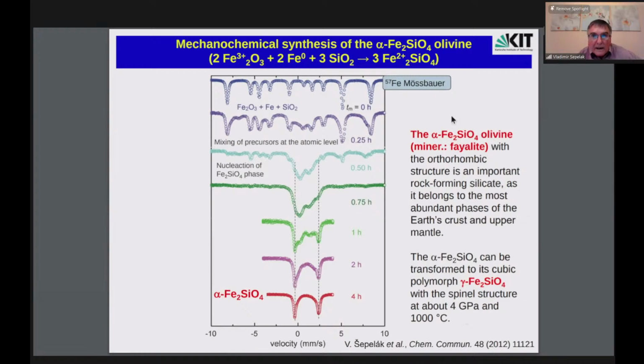But I only mention here its mechanosynthesis followed by Mössbauer spectroscopy. Again, we started with 3 precursors, and an internal redox reaction took place between iron 3+ in hematite and metallic iron with 0 valency. That means in the end we have iron in the divalent state, ferrous ions containing fayalite, and you see the mechanosynthesis was also very quick. 4 hours was enough to obtain